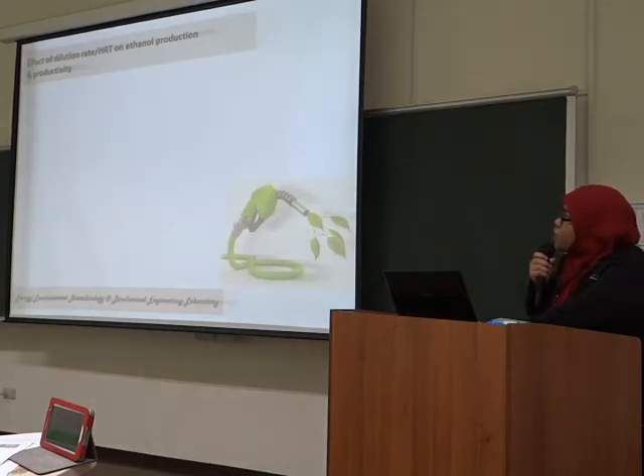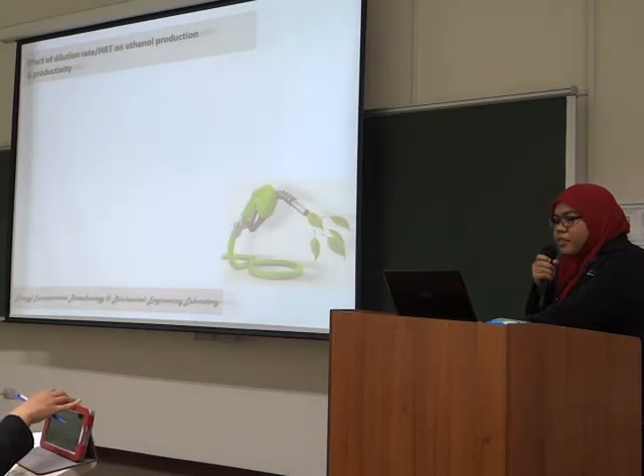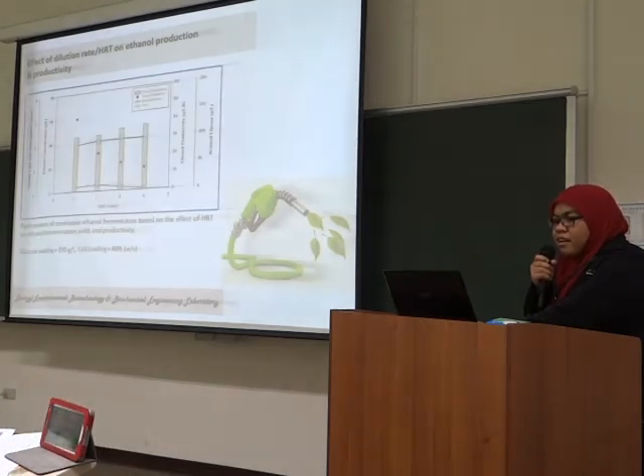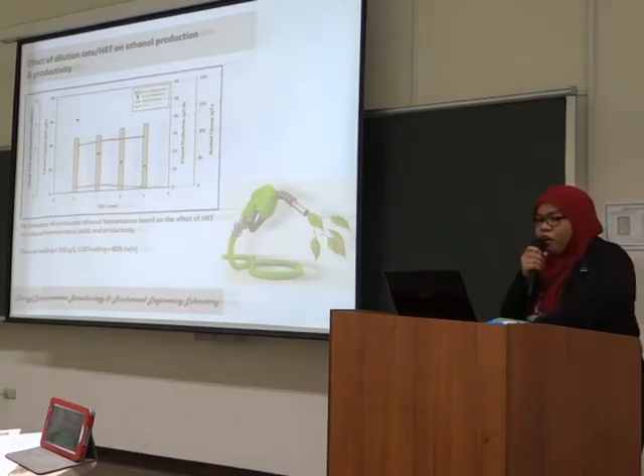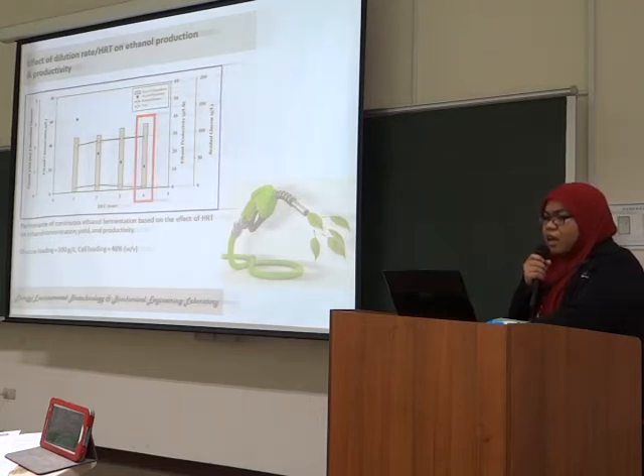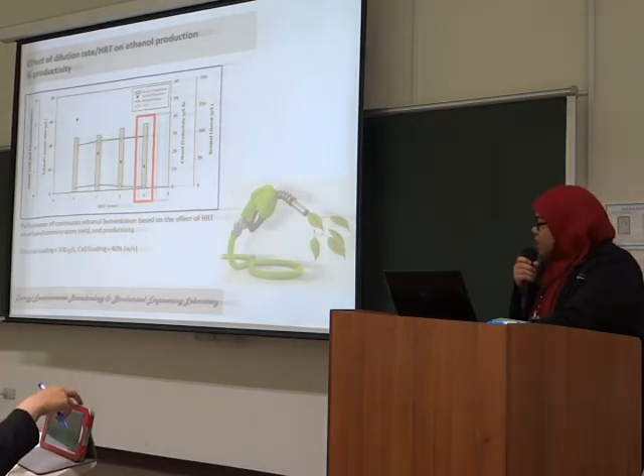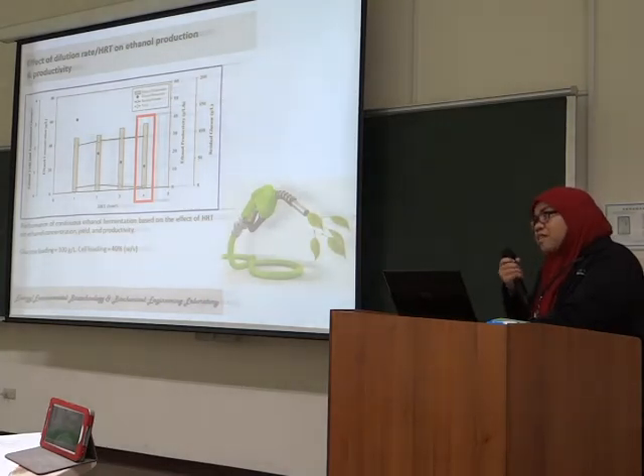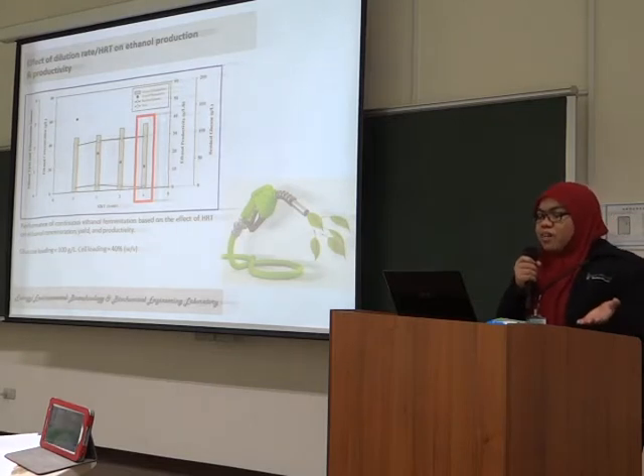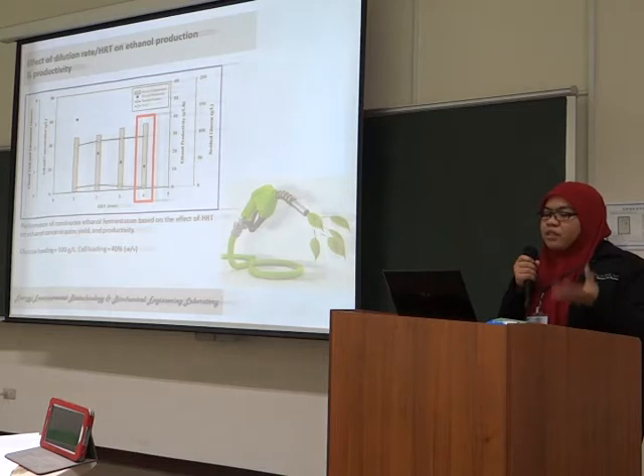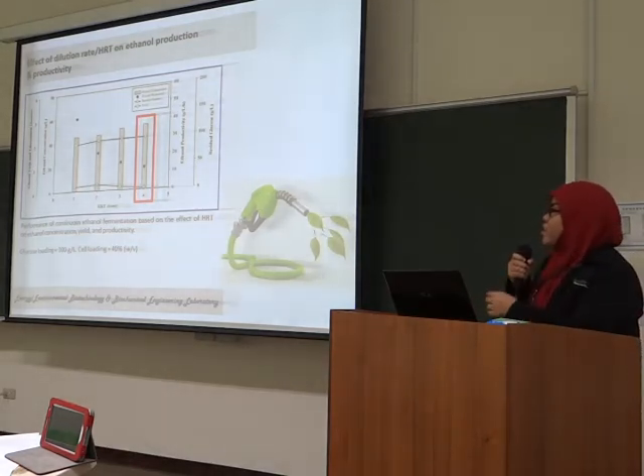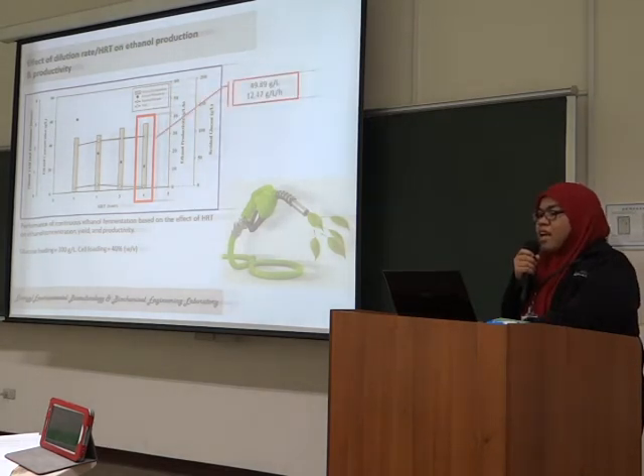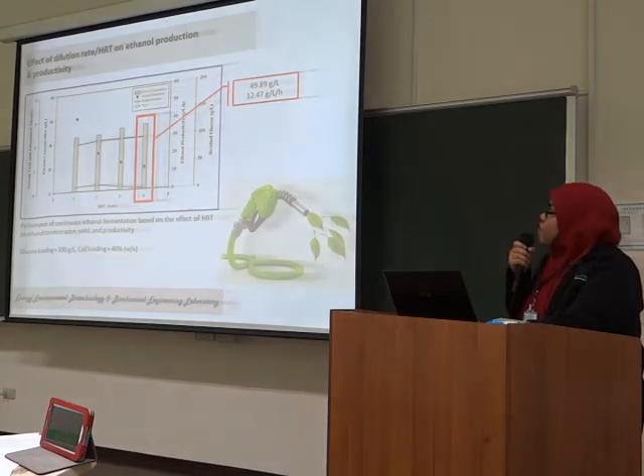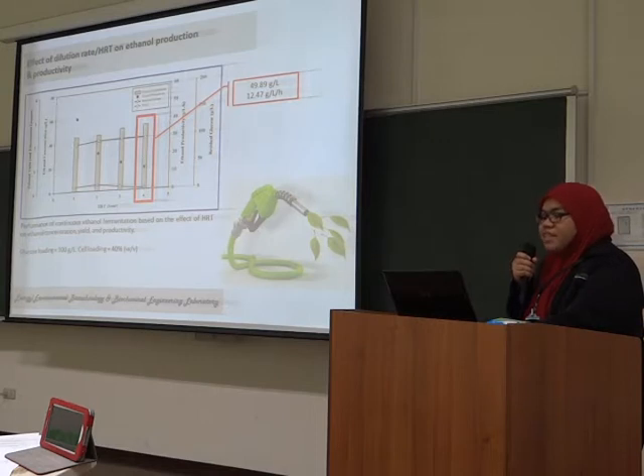And here I tried to investigate the effect of HRT or dilution rate on ethanol production and productivity. I chose 1 hour, 2 hours, 3 hours, and 4 hours of HRT. And in here, you can see the optimum condition should be at 4 hours of HRT. But we still can consider the 3 hours, because the residual glucose is only, if I'm not wrong, 6.05 gram per liter. But due to the cost issue, because the glucose is a little bit expensive, in here we choose the 4 hours of HRT as the optimum condition with the total ethanol production 49.89 gram per liter and ethanol productivity 12.47 gram per liter per hour.